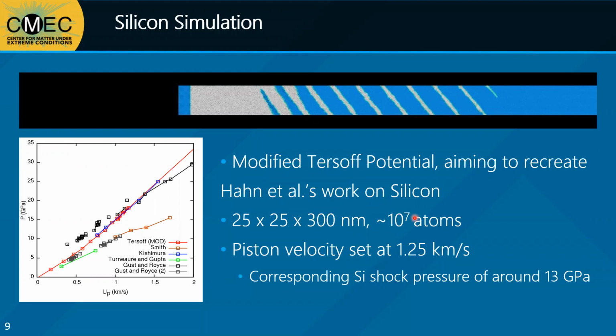Yes, for the phase diagram, the predicted phases for equilibrium silicon are around 10 GPa for the beta tin and around 11 GPa for the BCT5. But it is different for each potential. And for this modified Tersoff potential, the BCT5 was the lowest energy phase for these conditions. But there were several other phases that were quite close. The beta tin was quite close, and the Imma phase was also quite close. Okay, nice, thank you.